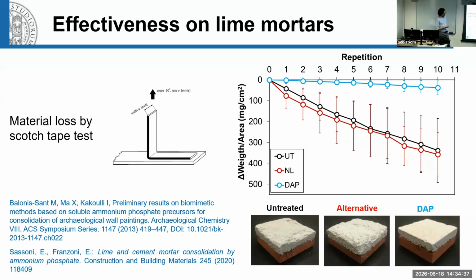We also tested mechanical improvement in the case of lime mortars, which are used in Europe, but also here. Recently, I've seen some very beautiful examples, for instance, also of wall paintings that are usually applied over a substrate and so on. So here, what we did was the so-called Scotch tape test, a peeling-off test, to measure how much material is lost when you attach an adhesive and then remove it. And again, with DAP, we are able to reduce the material loss significantly compared to the untreated reference or also some alternative commercial products. So also in terms of material loss by peeling tests, we found some good results.